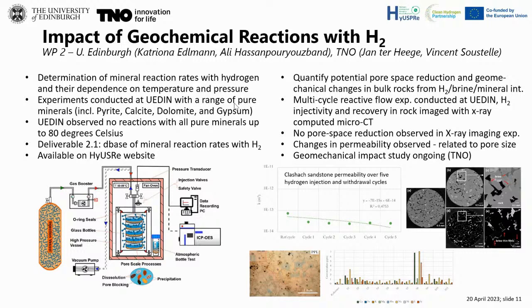These were conducted at Edinburgh on pure minerals like pyrite, calcite, dolomite, and gypsum, with a setup shown bottom left here. Quite an interesting setup, which allows for a lot of simultaneous batch experiments. And they observed essentially no reactions with all pure minerals up to 80 degrees in their setup. And the deliverable here is a database of mineral reaction rates with hydrogen. It's available on the HyUSPRe website.